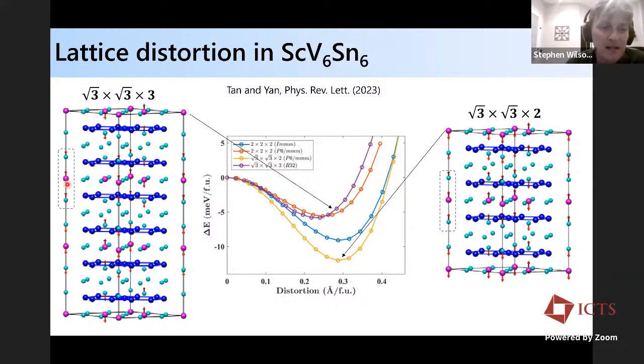And the key building blocks of this distortion, as I mentioned earlier, it's a sort of chain-like instability. You can see that the main motion of the atoms is really along the c-axis, between the Kagome planes of these tin and scandium ions, which move collectively together in what I'll call little trimer units, either up or down along the c-axis along these chains.